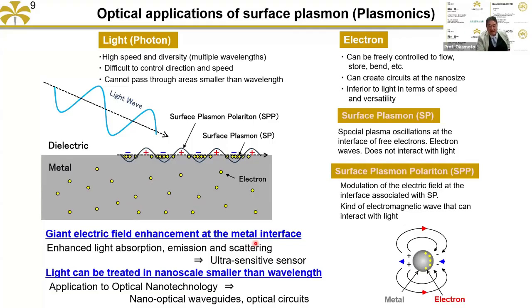That's one advantage. The other advantage is that the light can be treated at the nanoscale because it's strongly confined, coupled with the electrons. That's why it's much better. You can treat the light at scales smaller than the wavelength. Then you can use that for optical nanotechnology, nano-optical waveguides, or optical nanocircuits. So yeah, that's a very important merit. And if the surface plasmon is generated at the metal interface, it's a propagating mode, a two-dimensional propagation mode. And if the surface plasmon is generated at a metal nanoparticle, in that case, it's a localized surface plasmon mode. So surface plasmons have these two modes.